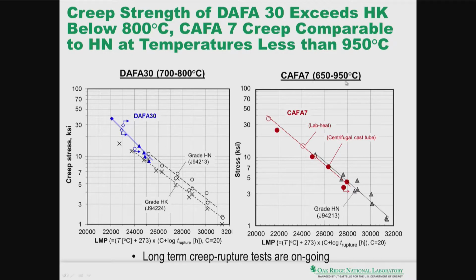The CAFA 7 has tests running between about 650 to 950 C so far. Here is the Larson-Miller plot, and this data point that's shown with an arrow is an ongoing test with an anticipated lifetime of about 10,000 hours. But as you can see, it is performing comparable to the HN at these temperature ranges.